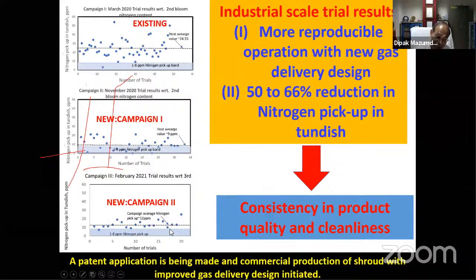But this also essentially indicates that we have about 12 ppm of nitrogen pickup, because the data set is small. So I think this 12 ppm can go down further to 8, 9 ppm, once we have a large number of data and so on.